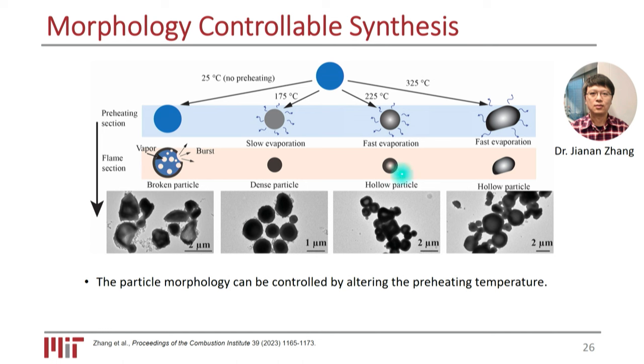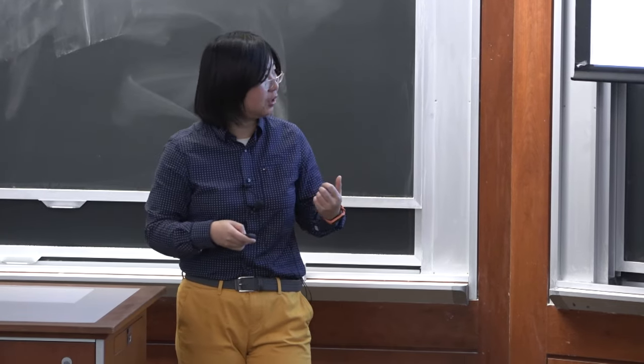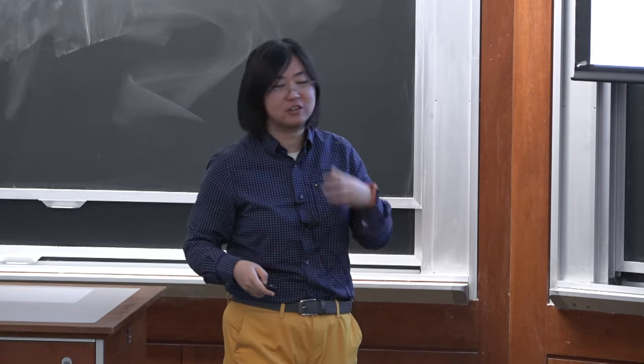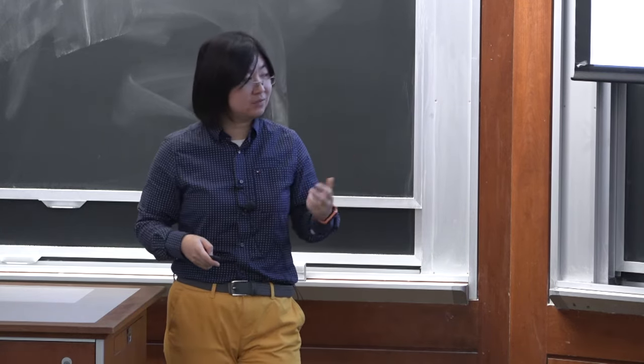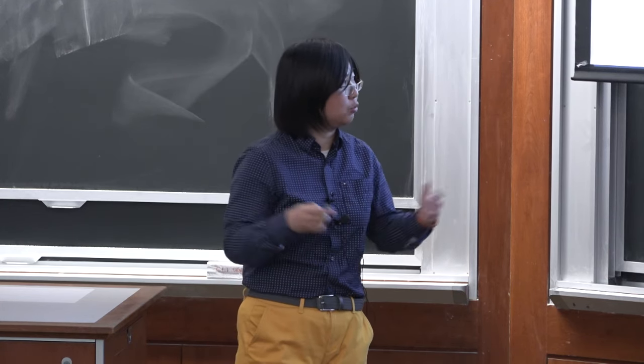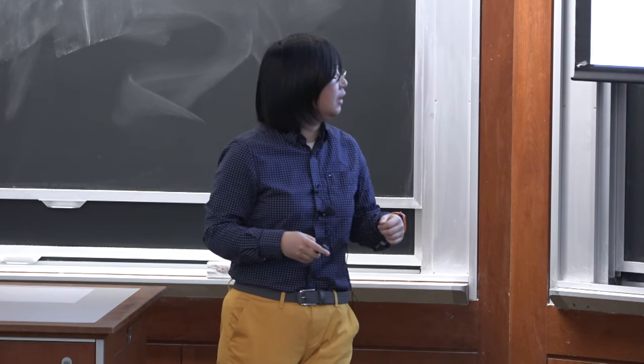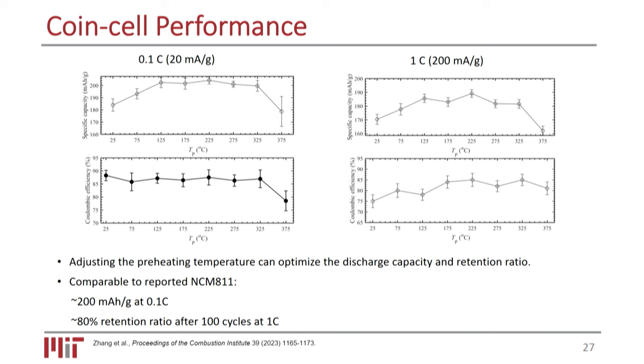But we want to relatively maintain these, but also have some flexibility for further design. By combining the flame section and preheating section, we can get either dense particles, very solid ones, versus these hollow ones. You see that the center is a little bit lighter in color. So we actually have a shell of the material rather than the fully dense material. That also gives us some space if we want to further do morphology engineering to achieve certain performance or to accommodate special needs when we assemble things together. But nonetheless, we do have a good temperature window where we can achieve relatively good retention ratio as well as capacity.